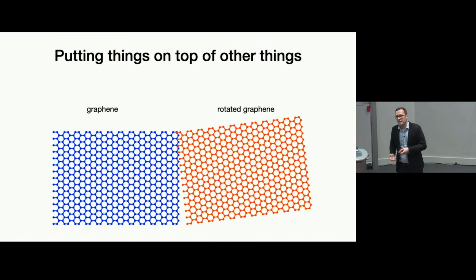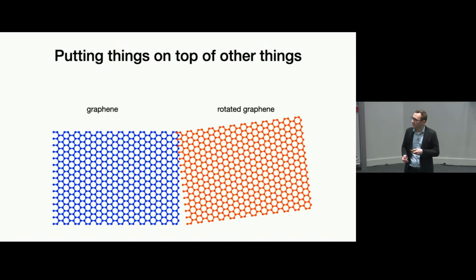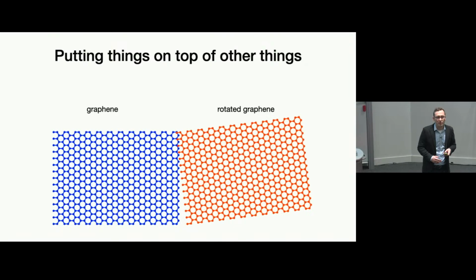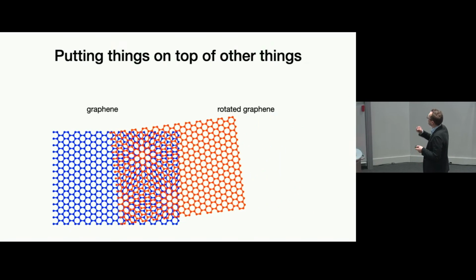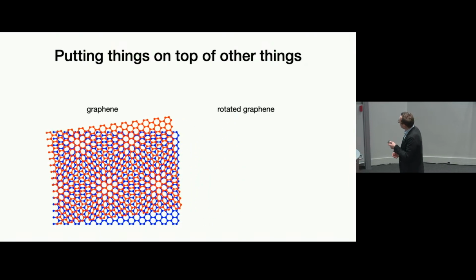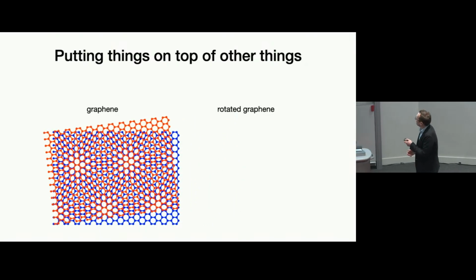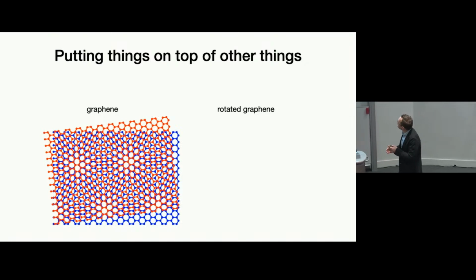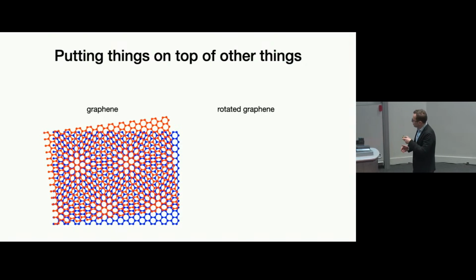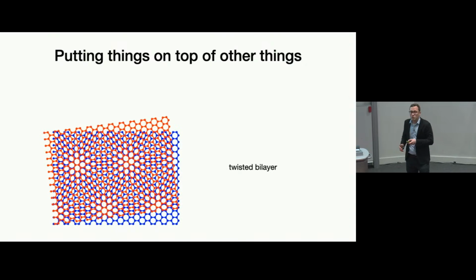But there are yet other ways that we can put two graphene sheets on top of one another. For example, what we can do is we can first rotate one of the graphene sheets and then put them on top of one another. And when we do that, something quite different happens. So what we get are regions where we have the AA stacking, where the carbon atoms sit directly on top of one another, and these regions of AB stacking here, like this one, for example, or like this one, right? So this is what we call a twisted bilayer.